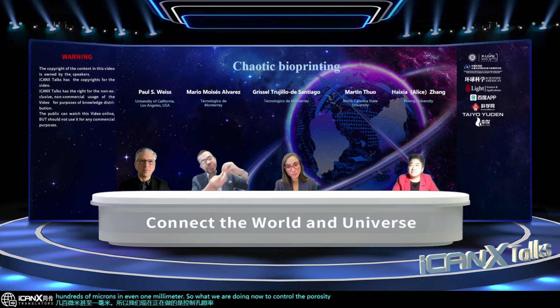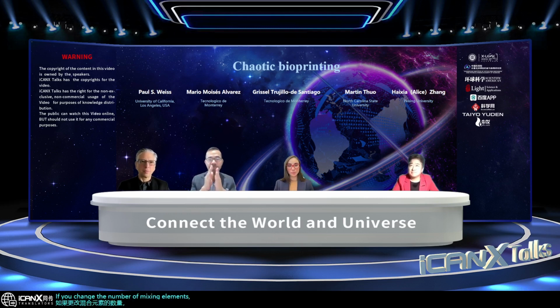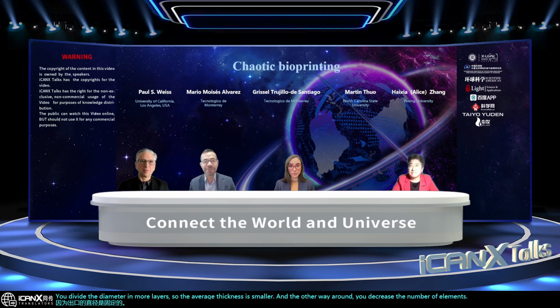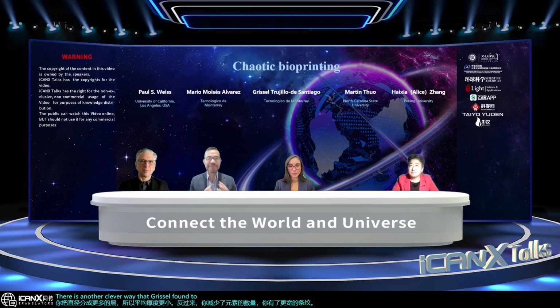If you change the number of mixing elements, then you will go for more layers. Since the diameter at the outlet is fixed, you divide that diameter in more layers, so the average thickness is smaller. And the other way around, if you decrease the number of elements, you have wider striations. But there is another clever way that Grissel found to control the porosity in a different way.